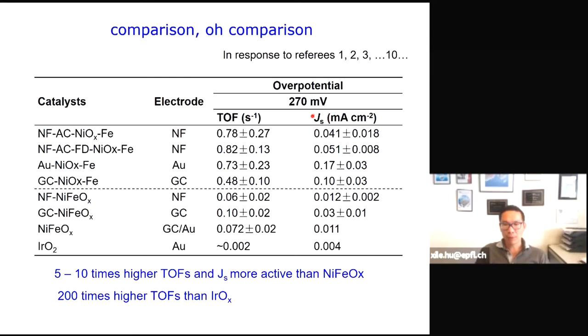So we can also use other parameters such as specific activity. This is the current density divided by electrochemical surface area. We can also use the overpotential for a given current density, which I will show you in the next slide. And so we find that consistently we can make the best nickel iron oxyhydroxide catalyst. Our turnover frequencies and specific activity are typically 5 to 10 times higher than this nickel iron oxyhydroxide. And if you really want to feel good, you can compare to iridium oxide, because it's actually not so good a catalyst. So we get hundreds of times higher activity in the lab.